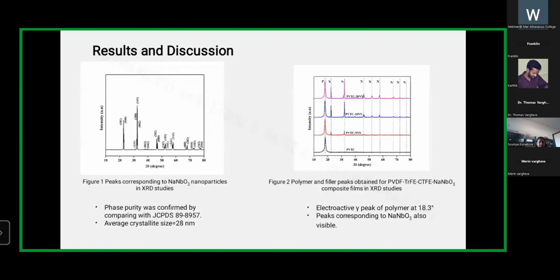And coming to the results, the XRD results obtained for sodium niobate nanoparticles confirmed its purity, and it was also confirmed by comparing with the JCPDS data. The average crystalline size was found to be 28 nanometer. Coming to the XRD data of the composite films, we can see the presence of the electroactive phase of the polymer in each composite film, and also the peaks corresponding to sodium niobate get enhanced with the loading.